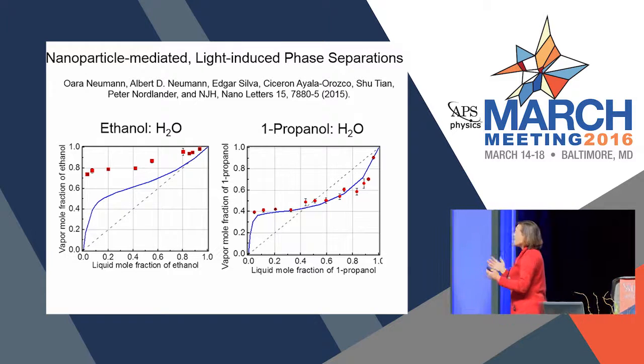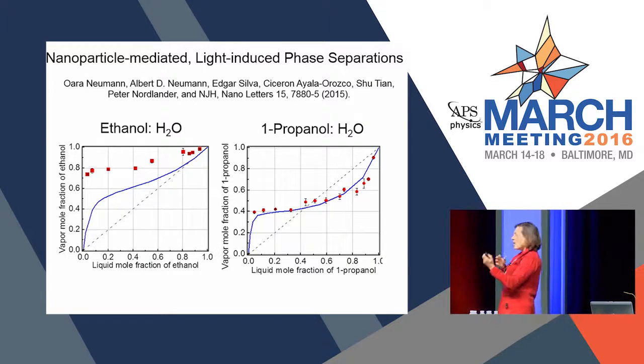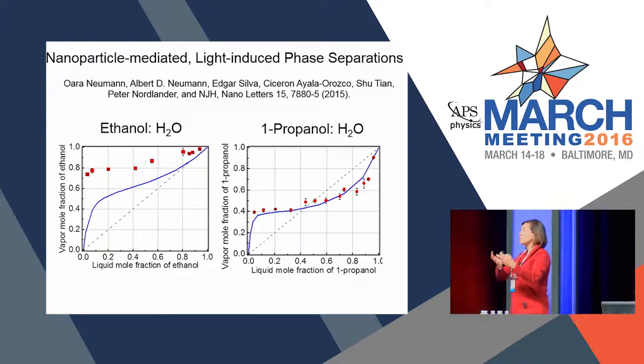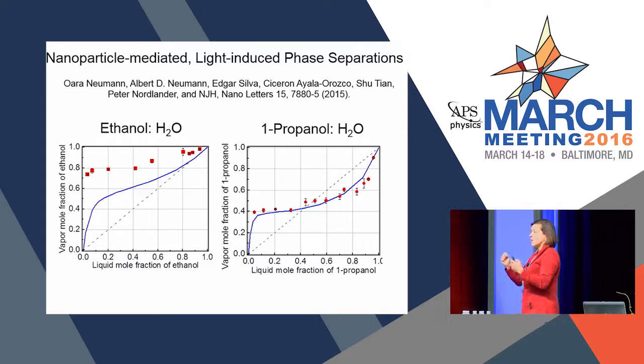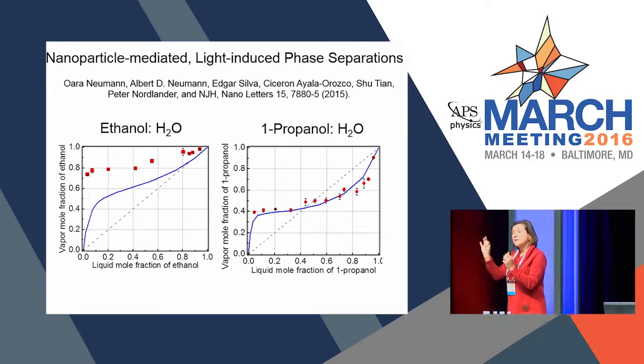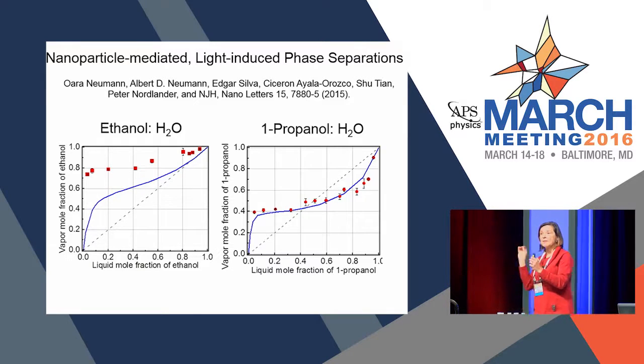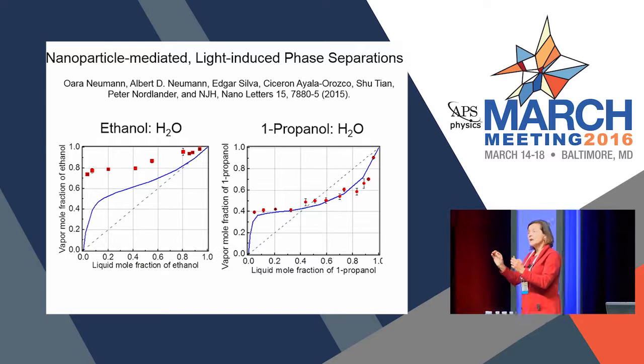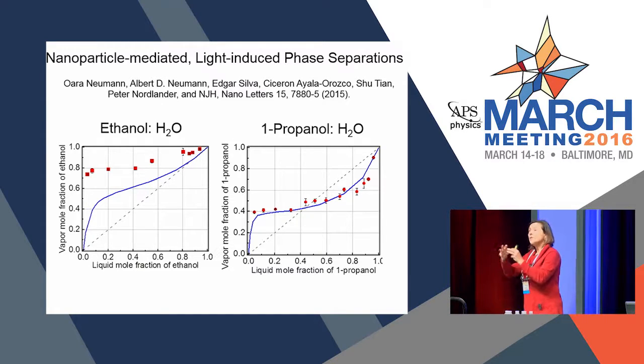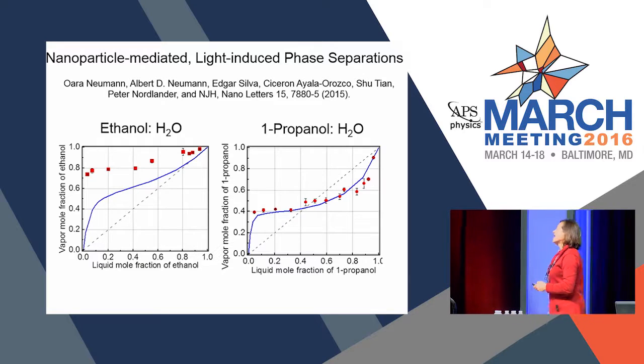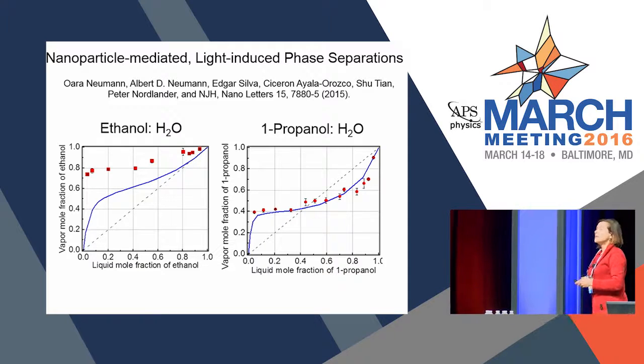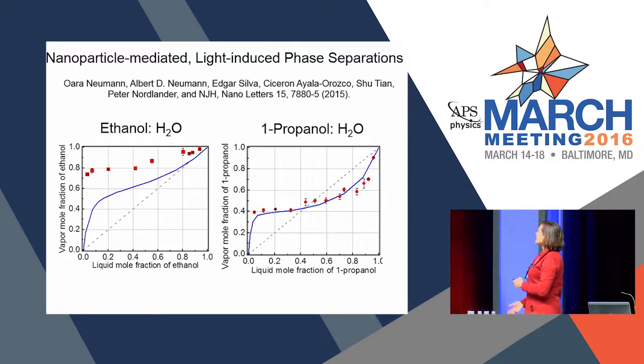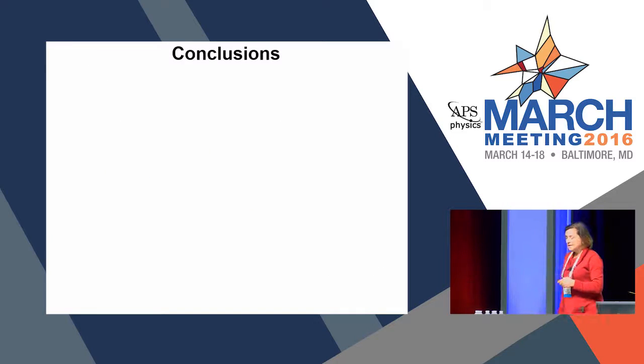Now, why is this? We understand this because water ethanol forms a very strongly hydrogen bonded network. Propanol and water form a much weaker hydrogen bonded network. And what we're doing is we're distilling with these little nanoscale heaters. And so we believe that the mechanism is very strongly tied to the fact that they can disrupt the local hydrogen bonding network. And that's the mechanism for the enhanced ethanol vaporization that we see in this experiment.